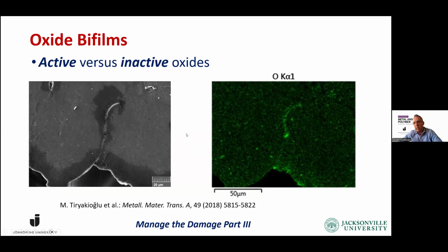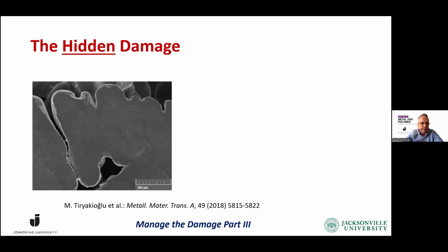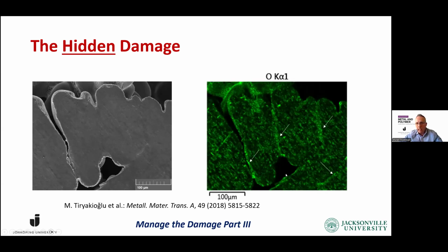And then we started looking for these hidden bifilms. We went to another location on the same micrograph. It looked curious. Okay, turn the X-ray map on, and they are everywhere. As you can see, there's some here, there's some there, there's another one here, there's another one there. So all these bifilms are hiding right in front of us. There's a huge pore, but the pore did not expose all the bifilms. So it's clear that the overall damage is more extensive than what we can see with the pores. And that started our thinking. Well, okay, if that's the case, if we get rid of the pores, do we get rid of the damage? And obviously the answer is no.